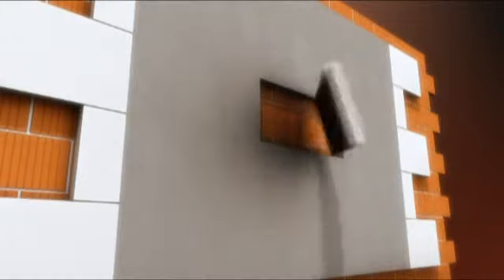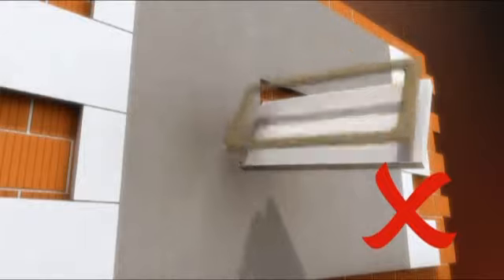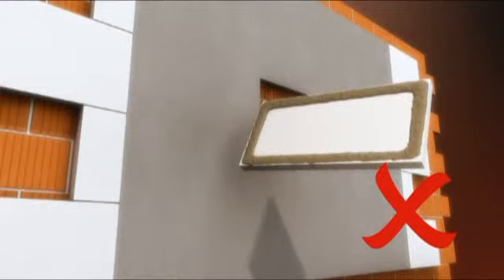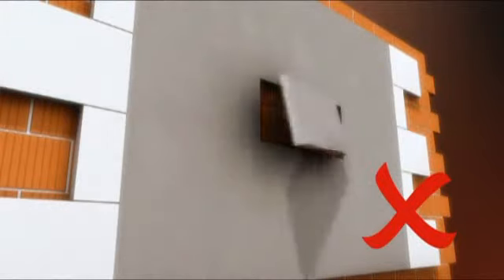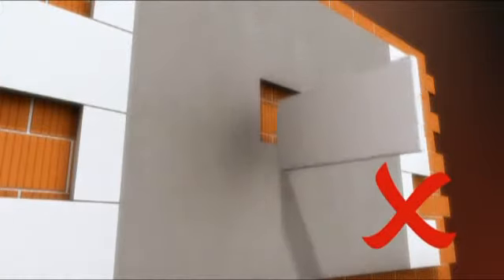By applying adhesive to the middle of the board, any deformation is prevented from forming as a result of harsh temperature conditions, which are shown in the following animations. In the case that adhesive mortar has only been applied to the borders of the board, there is a great possibility that, because of the effect of temperature, surface deformation known as board blistering will occur. In the long run, this defect can lead to the insulation boards becoming detached from the facade.